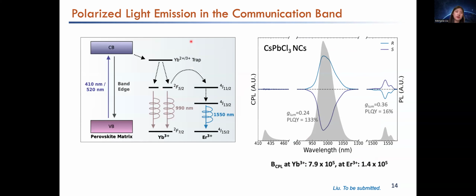We have tested this material and the highly efficient energy transfer has been proved. So this allows us to get a quantum efficiency above 100% in the near infrared. Using the dopants ytterbium and erbium, we can get emission around 1 micron and 1.5 micron. And also, because of this surface distorted lanthanide dopant, we get a very high dissymmetry factor, around 0.24 in the near infrared and 0.36 in this communication band.